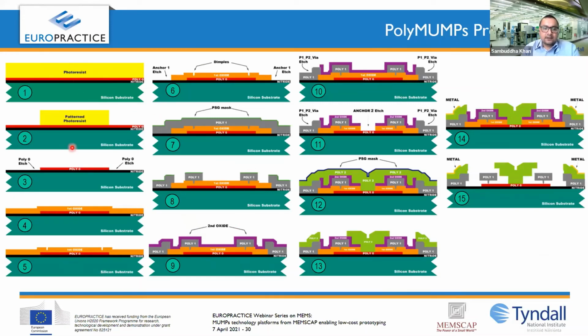First the poly 0 deposition, then oxide deposition, and oxide patterning for making the dimple. There is a mask called dimple, and once the dimple mask is defined, the first oxide is selectively etched, followed by the poly 1 deposition. Once poly 1 is deposited and etched selectively, you go for the second layer of oxide deposition, selectively etch the oxide, and then the anchor 2 creation.